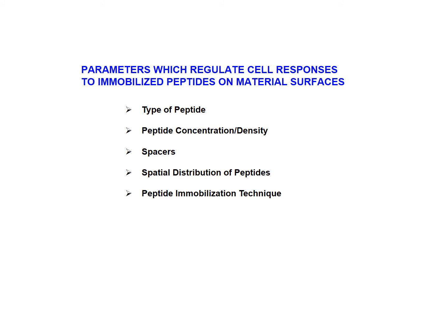For that purpose, what researchers in the field did is to use what we call extensions, and that meant that we added more amino acids which did not have adhesive properties, but at the very end, at the top, the one area which comes in contact with the receptors on the cell membrane, that was the place where the RGD or the other respective peptide was immobilized.